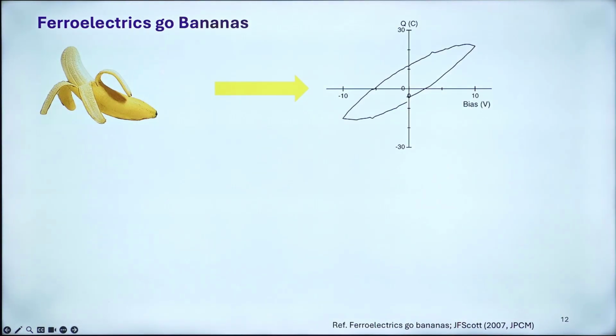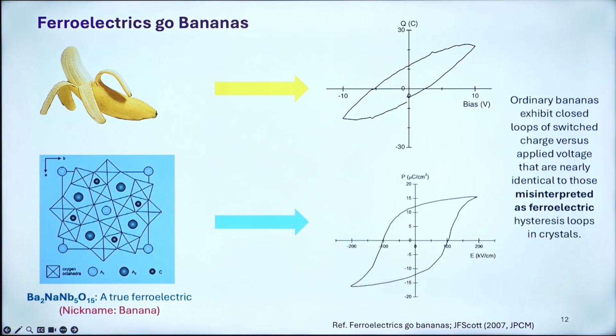And then people normally, okay, so this is something interesting which I started learning while doing this PowerPoint. Ferroelectrics go bananas, so often we are misguided by the loop which we see. So for example, this is a true ferroelectric loop, nickname banana they call it, and then you get something, a loop which is not a precise hysteresis. So they say the ordinary bananas exhibit a closed loop of switched charge versus applied voltage that can be nearly misinterpreted as ferroelectric, okay.